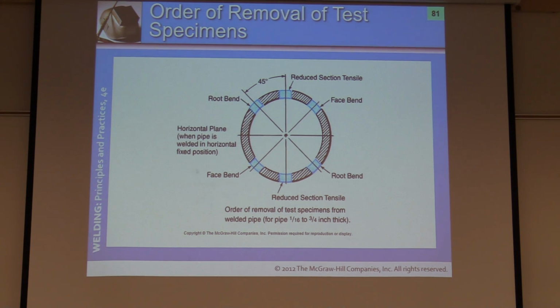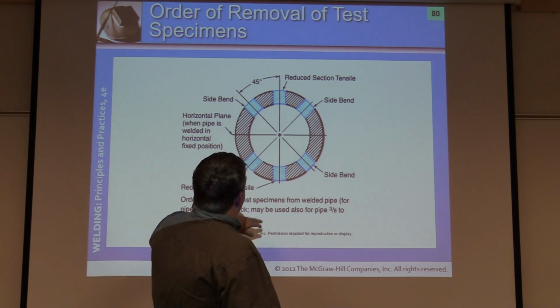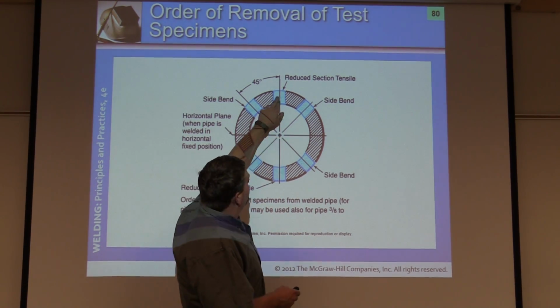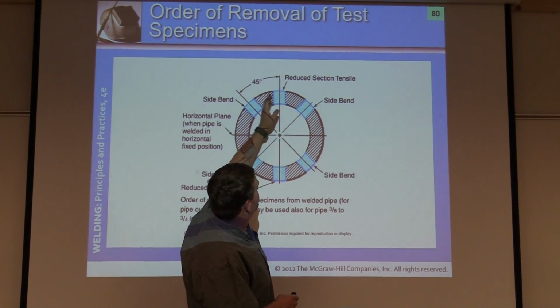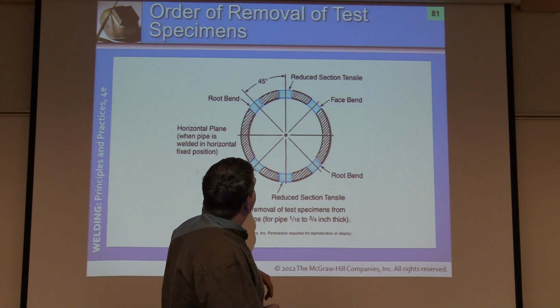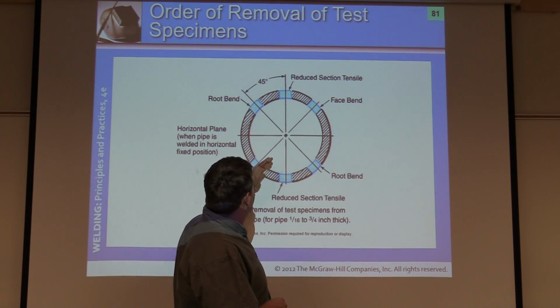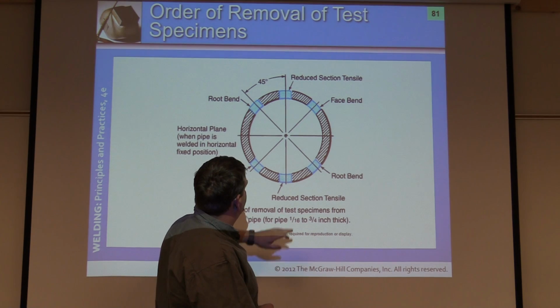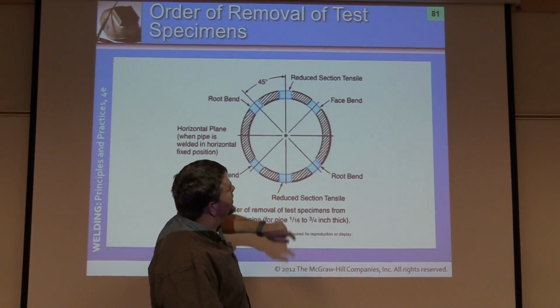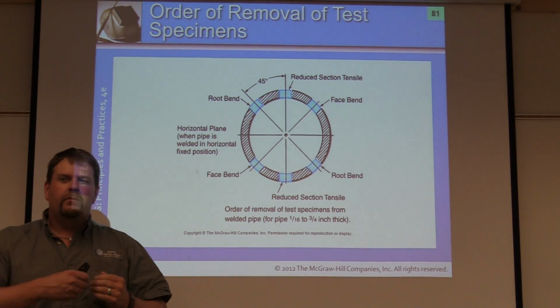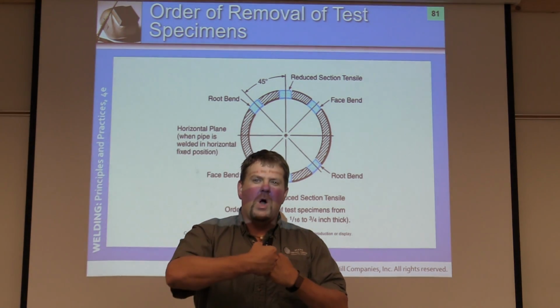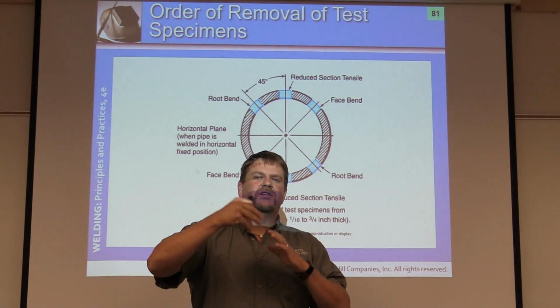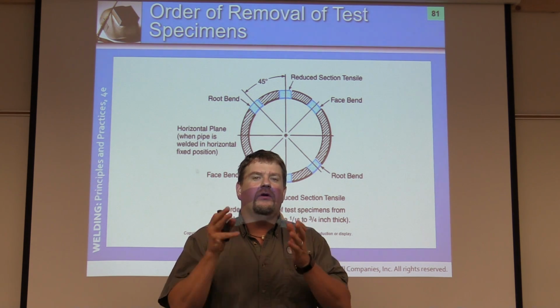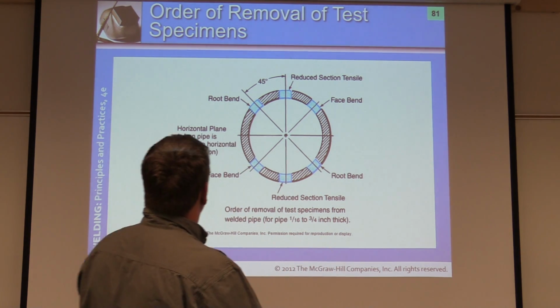So here's a good example. This is what we do in the shop. This one's for the procedure qualification record versus the welder performance. Same as this. For a welder performance, we don't have to pull the reduced section tensile, we just have to pull the 4 side bends, okay? For welder performance, we just pull these 4. Procedure, same thing. We have to check the mechanical properties of it, making sure the tensile strength of the weld still meets or exceeds the tensile strength of the material that has been welded, okay?